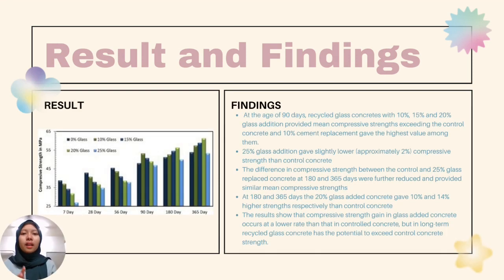So these are the results and findings for the compressive strength test on the concrete. The compressive strength of recycled glass concrete, from 0 up to 25% glass addition at different ages, is shown in the figure of the result. At the age of 90 days, recycled glass concrete with 10, 15 and 20% glass addition provided mean compressive strength exceeding the control concrete, and 10% cement replacement gave the highest value among them. 25% glass addition gave slightly lower compressive strength, approximately 2% lower than the control concrete.